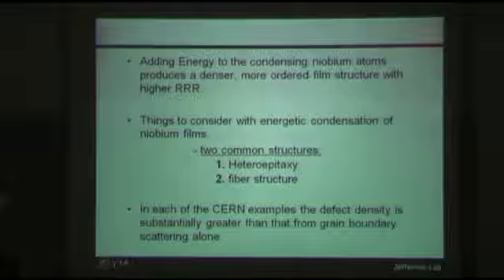For this mode to be useful, the fiber width can't be too small, such that grain boundary scattering dominates the electronic mean free path. The density of nucleation sites at the substrate needs to be understood and controlled in order to attempt to get a larger grain size.